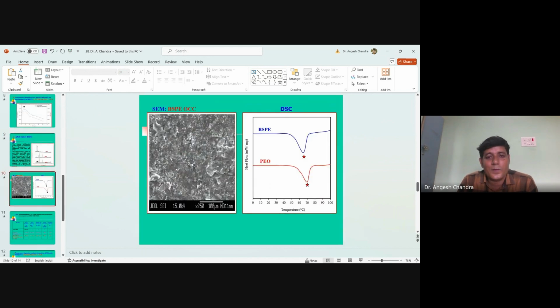Now this figure shows the surface morphology of the blended solid polymer electrolyte optimum conducting composition. This shows a smooth surface morphology, while the pure PEO shows a very rough type of surface morphology. The second figure shows the differential scanning calorimetry, and this endothermic peak shows the melting point temperature.